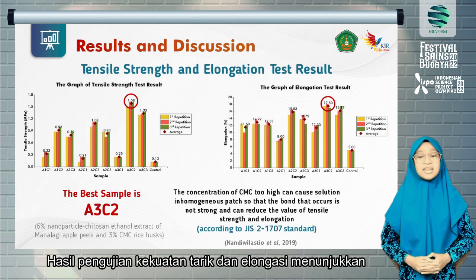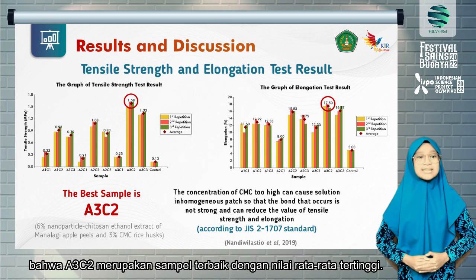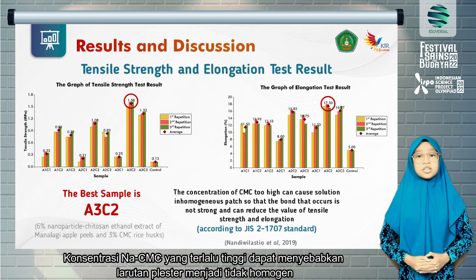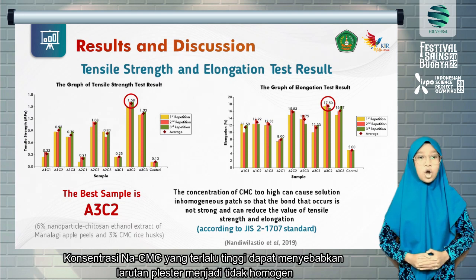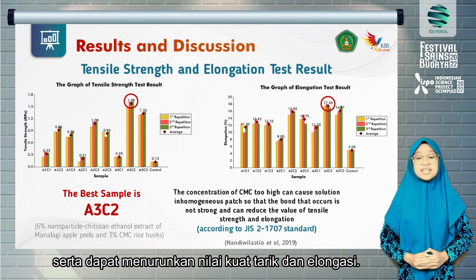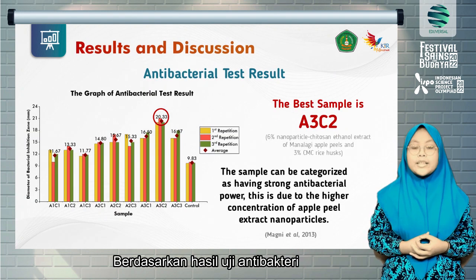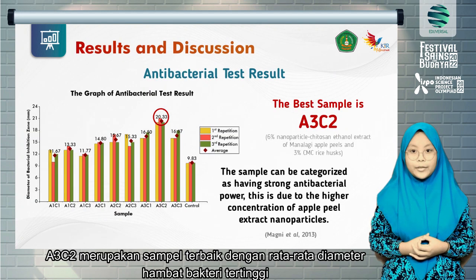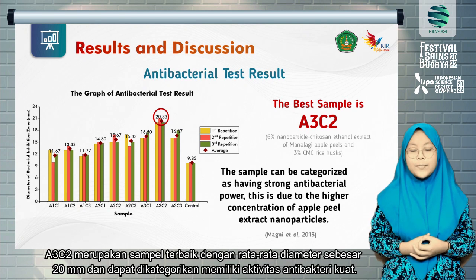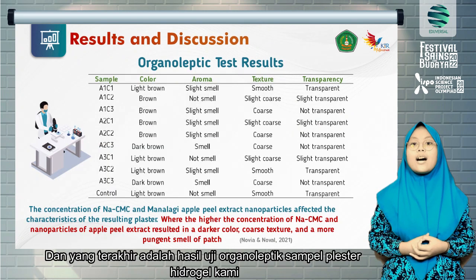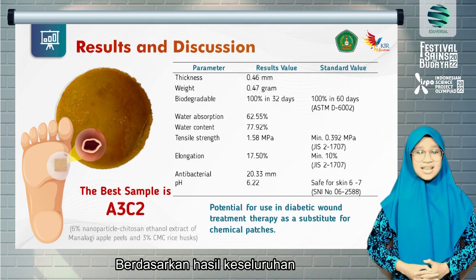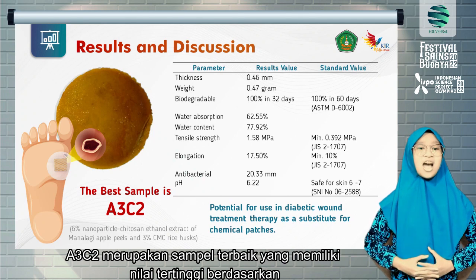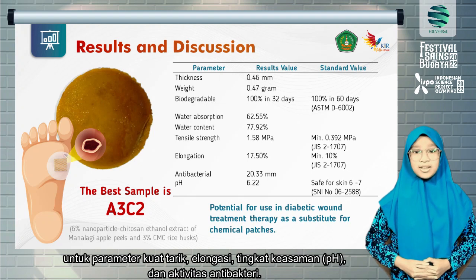The tensile strength and elongation test result shows that A3C2 is the best sample with the highest average value. A high concentration of CMC can cause a non-homogeneous patch solution and can reduce the value of tensile strength and elongation. Based on antibacterial test results, A3C2 is the best sample with the highest average diameter of bacterial inhibition of 20 mm and can be categorized as having strong antibacterial activity. And the last is the organoleptic test result of our hydrogel patch samples. Based on the overall results, A3C2 is the best sample which has the highest values for the parameters of tensile strength, elongation, acidity level, and antibacterial activity.